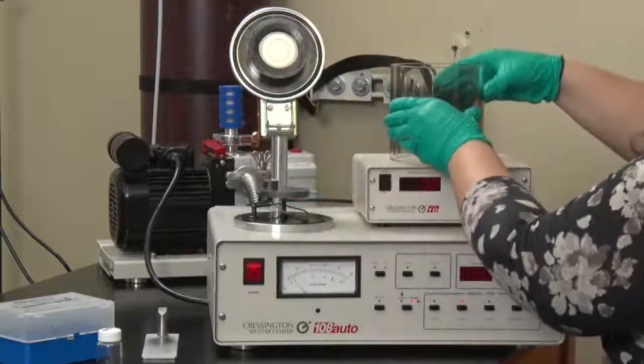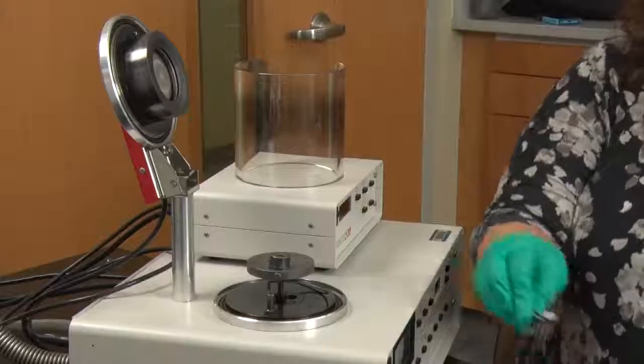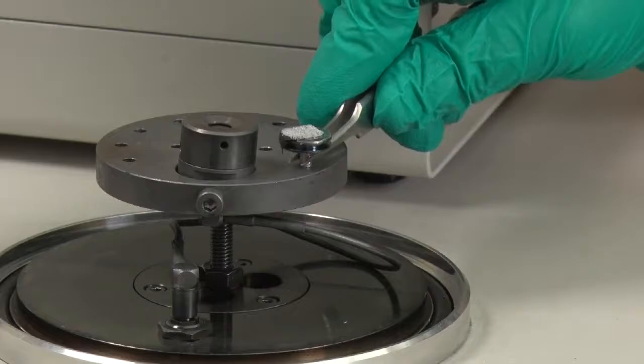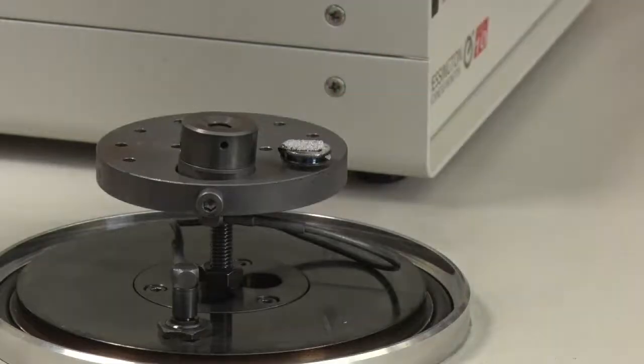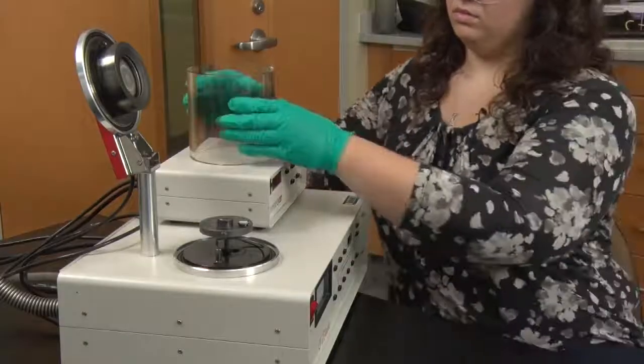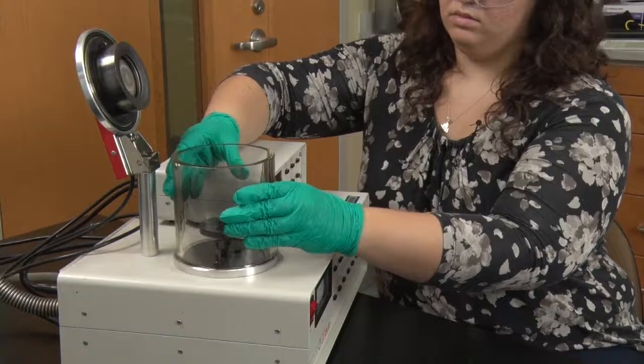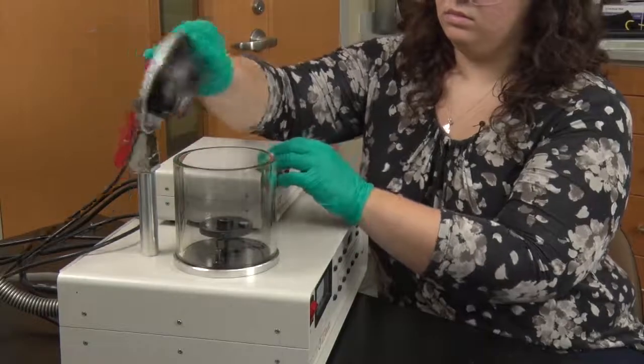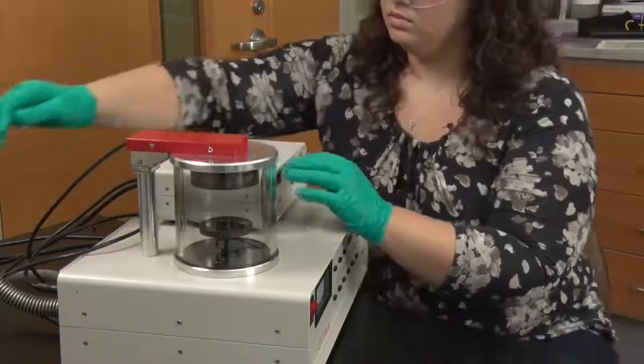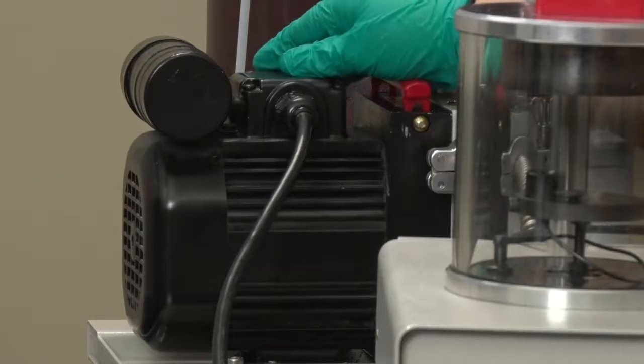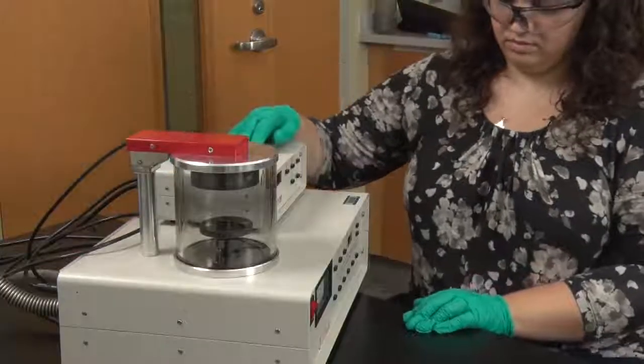The metal that we will deposit is actually held in the lid, and this small circular disc just next to the sample is called a quartz crystal microbalance. It can measure how much material has been deposited. After loading the sample into the chamber and closing the lid, I can evacuate the chamber using a vacuum pump. Once the chamber has been evacuated, I can start the deposition.